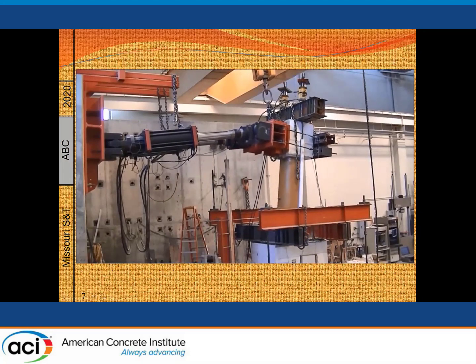And on this particular test, we actually went up to 13% drift. And here, we inserted a camera inside the columns. So this displays the elastic buckling of the tube. So you would see here compression and buckling of the tube. And then once you reverse the load, the steel goes up again and stretches back.